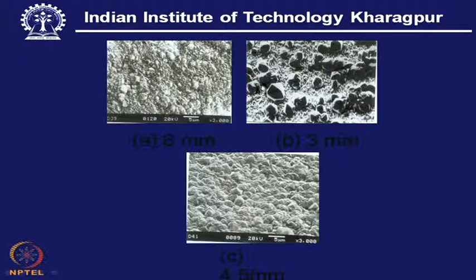And here we can see well developed crystals, individual crystals larger than this one, and that we will also get from SEM, but this is not covering fully. So, this is actually a carbide substrate. This is an exposed carbide substrate, it is fully covered, but not a good morphology. This is one of the very good morphologies, and here we have discrete deposition. That means this SEM image clearly gives us information about nucleation centers or nucleation sites. So, nucleation density is not quite high here, but in this case nucleation density was quite high.